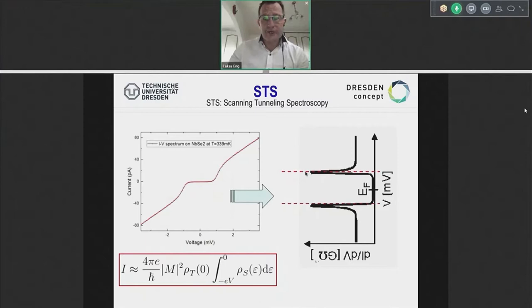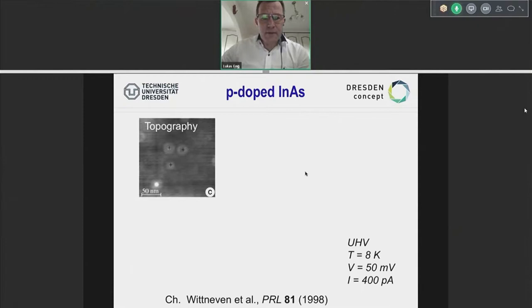Well, one prominent example I would like to show is something that the group of Roland Wiesendanger has also done lately. And this is actually work which is about 20 years old already, done by tunneling microscopy, or better to say, tunneling spectroscopy, using an indium arsenide semiconductor, as you see here, and using the p-doped version of that semiconductor. Well, topography in STM doesn't show too much. What you see is kind of dashes. Well, you don't really know whether these are artifacts or something else, but they could be protrusions.